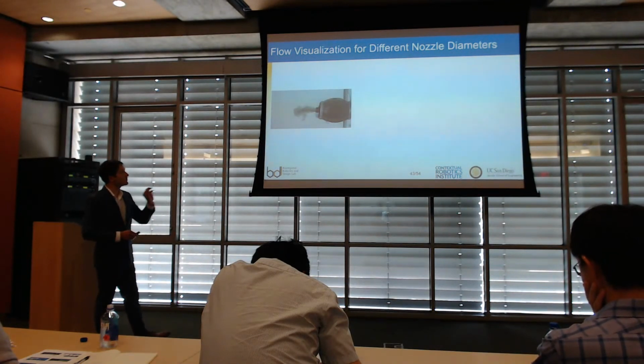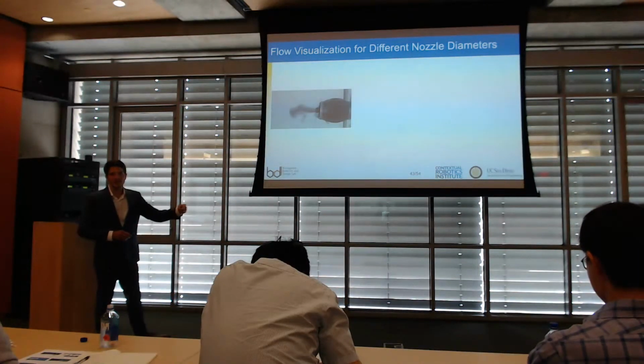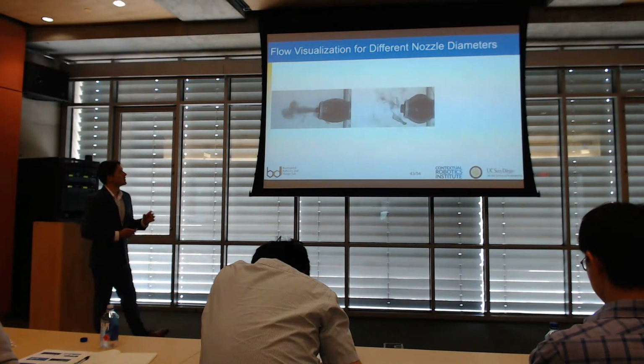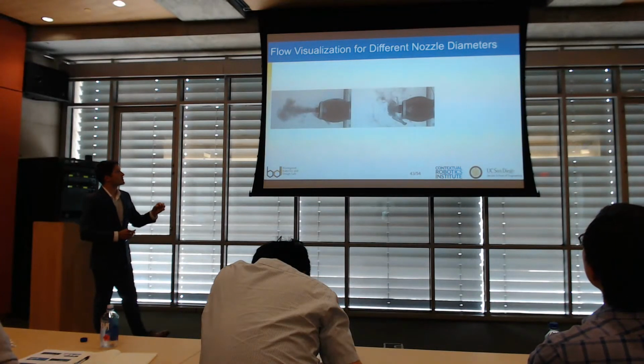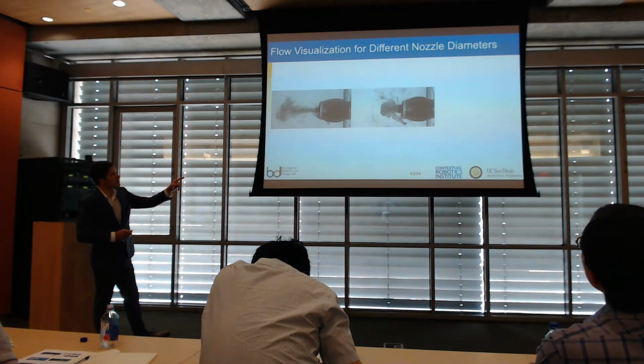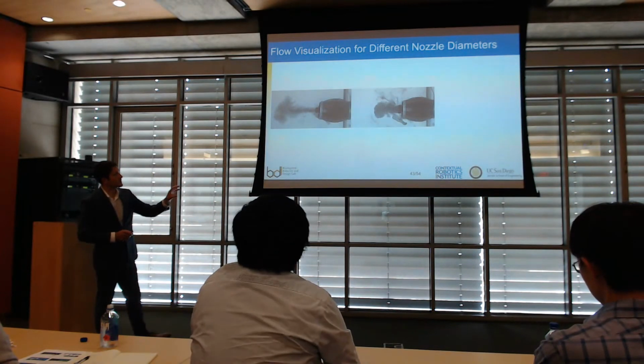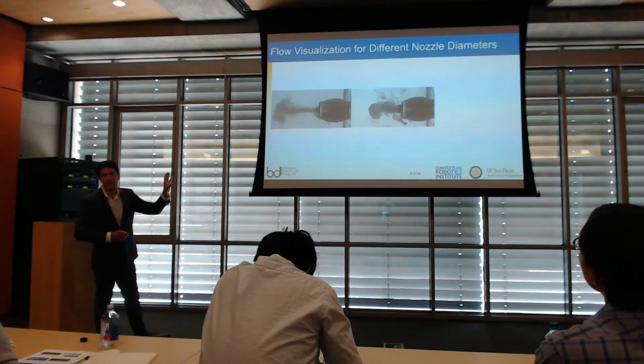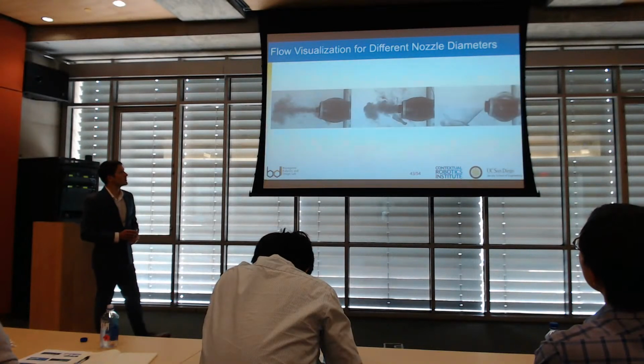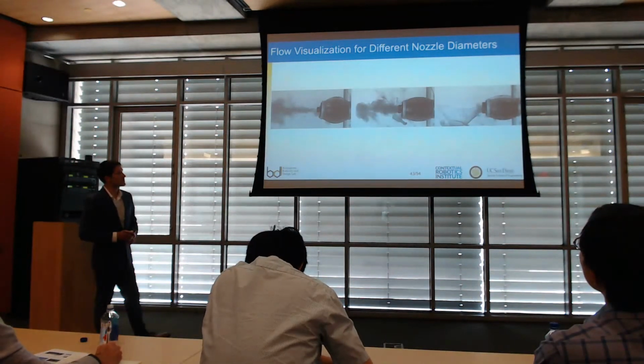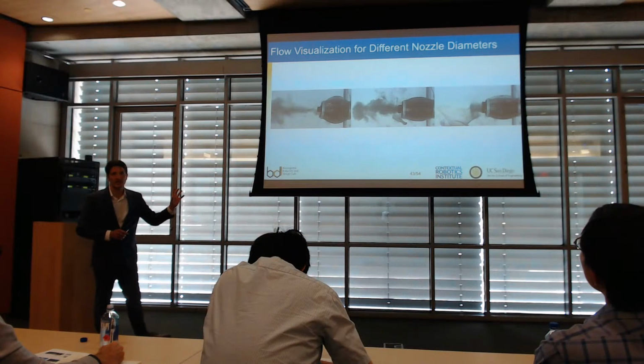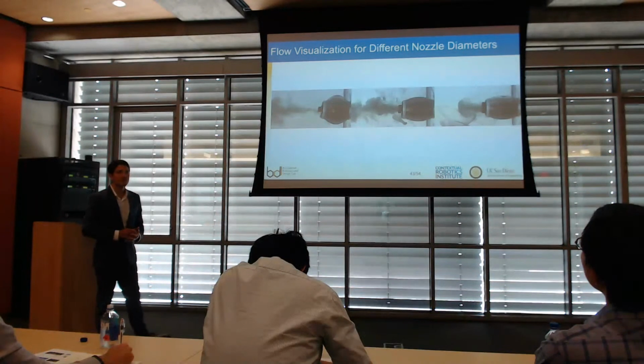So what you have is a stream of fluid that's moving so quickly that it doesn't have time to roll into a stable vortex ring. For the middle phase, it's closer to the ideal formation number. So you get this leading vortex ring that starts rolling up, but then there's still more fluid coming in behind that leads to secondary vortex rings. And then in the final case, when we have formation number close to 4, we get this nice stable leading vortex ring, and almost all of the fluid that comes out is entrained in that leading vortex ring. So that shows that this is the most efficient for this robot.